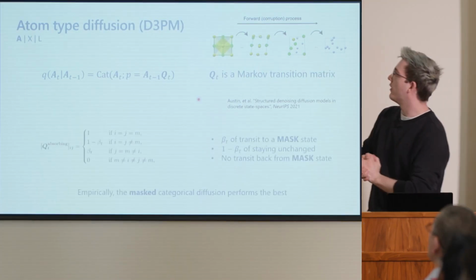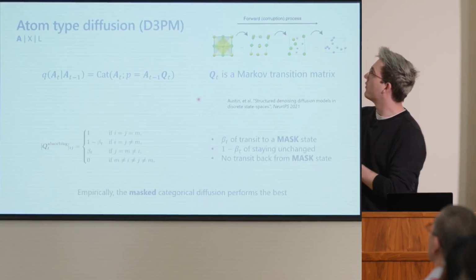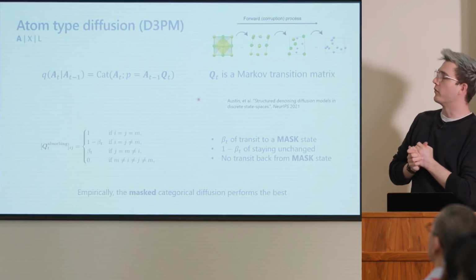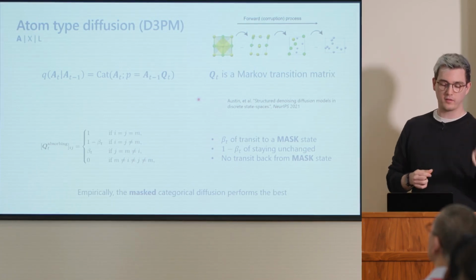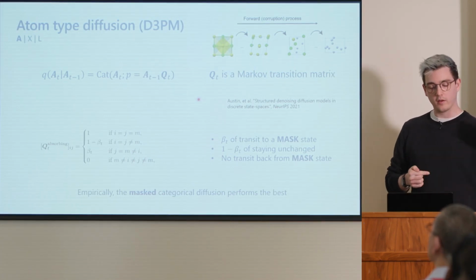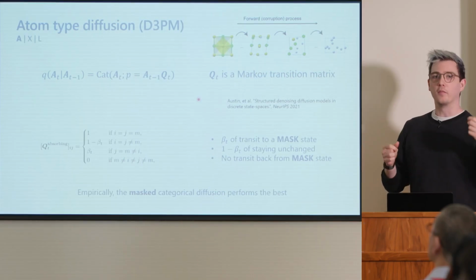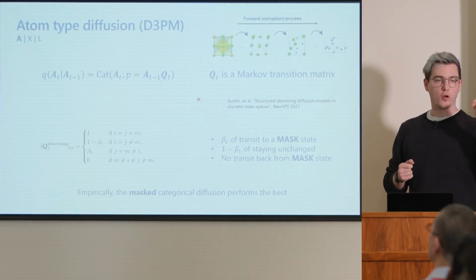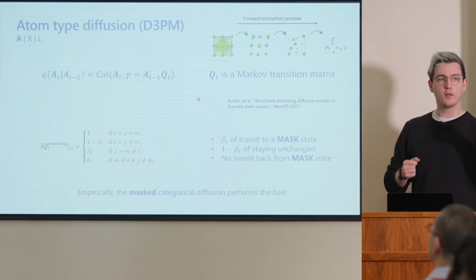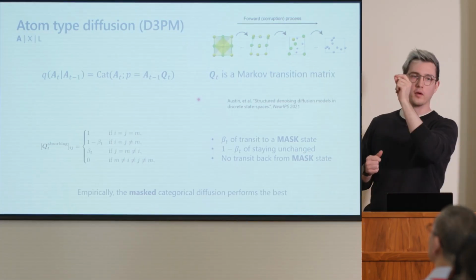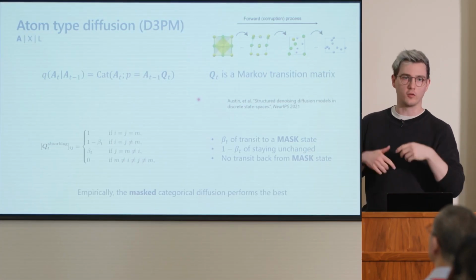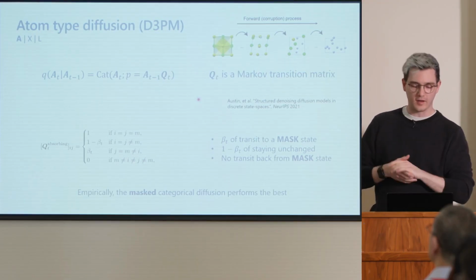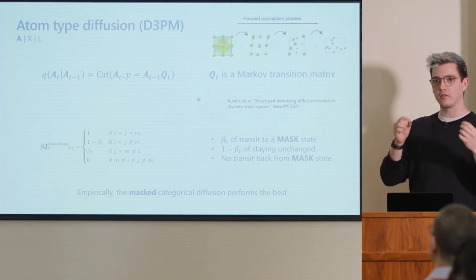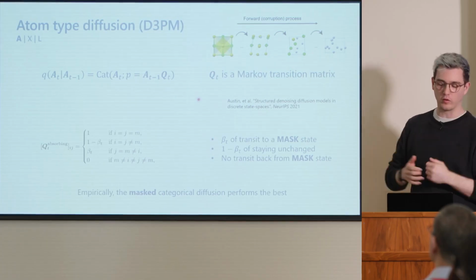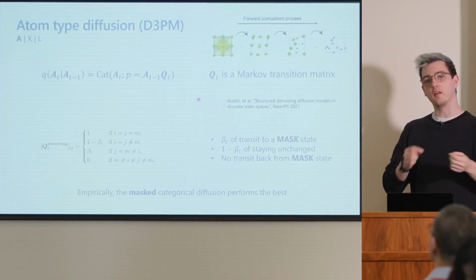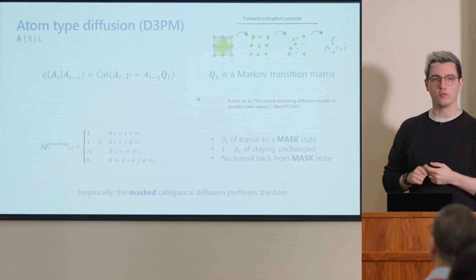The particular instantiation that we use is slightly different. We use what they call the absorbing or masked diffusion, where at any time step you just have some small chance for each atom that it'll transit into a masked state. So it's a non-physical state. It's not a known atom type. It's just something else, a masked or absorbing state. And once it's there, it'll stay there until the rest of the diffusion process.